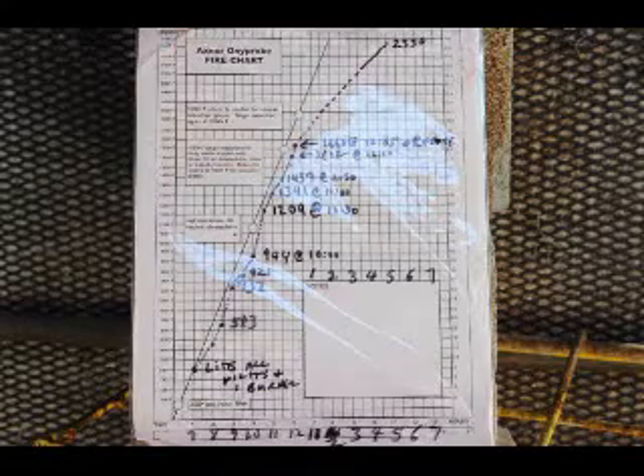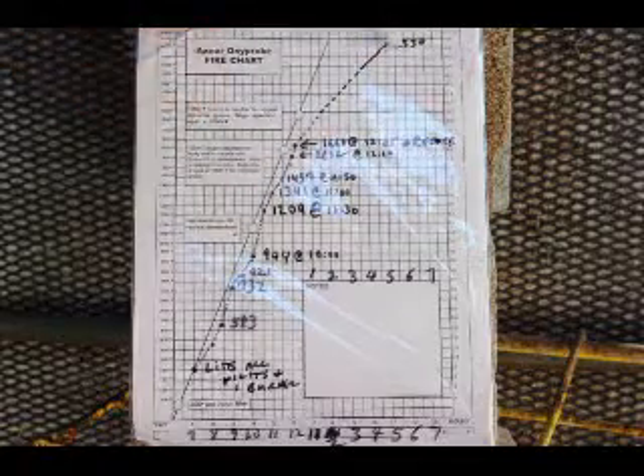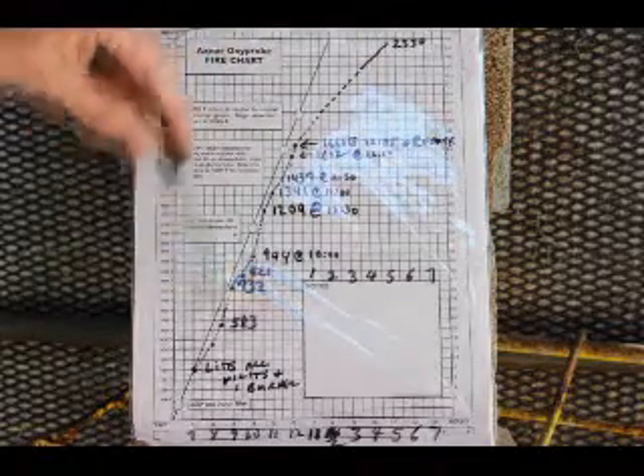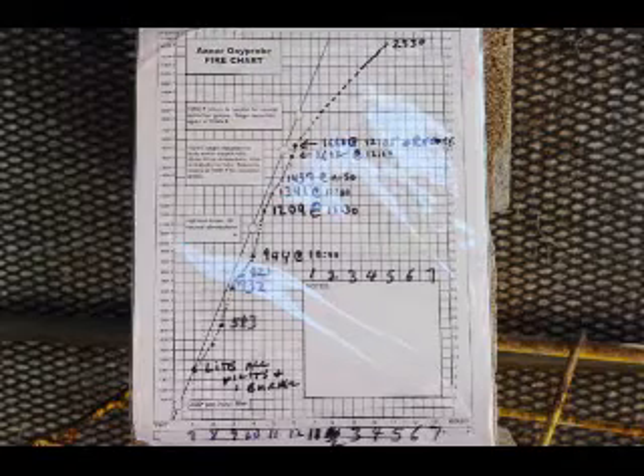Okay, 5 o'clock. Temperature got to 2330 according to the pyrometer, but cone 10 is flat and 11 is starting to bend slightly, so that went up very quickly. Actually, that's the fastest curve that I've ever had since I've been firing this kiln. So hopefully the reduction is satisfactory, and we'll take a look at that when I open the kiln in a couple of days.